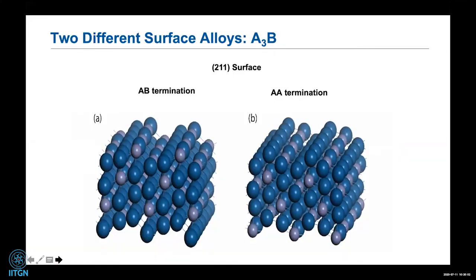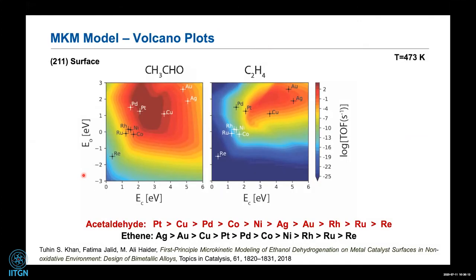We give different alloys A and B terminations: in B-termination there are more B atoms on the surface, while in A-termination the B atoms are buried in the subsurface. Both terminations are employed in the models. We solve about 50+ elementary reaction steps as ordinary differential equations, and the model gives final turnover frequencies. Showing the log of turnover frequencies with respect to the descriptors — oxygen binding energy and carbon binding energy — in a two-dimensional volcano plot, the most reactive elements lie in the red regions: platinum, palladium, and copper.